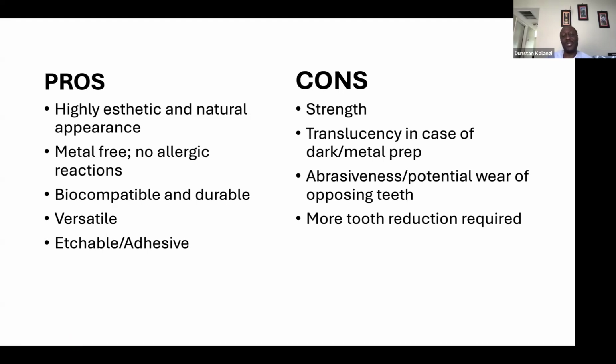What can I do? Be mindful of that. So in some cases, you might need to take what they call the stump shade. When you do a prep, you need to record the shade of the prep in some cases, especially if you're doing aesthetic work. Then you can tell your lab, the shade of my prep is this, but my patient wants this kind of shade. What do I do? If you're working with a good lab technician, they should be able to advise you. We can put an opaque core, but when you put an opaque core, you're going to sacrifice the translucency or the natural appearance of the crown that you're doing, especially if you're working at the front.